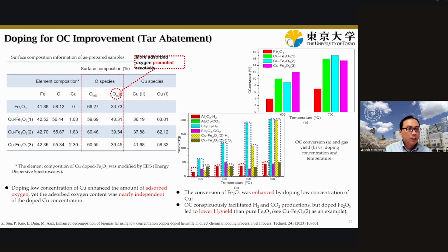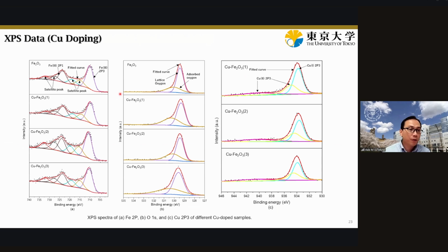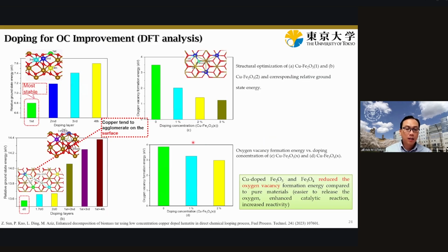This is also confirmed by XPS data: by doping copper into the hematite itself, the binding energy for the adsorbed oxygen atoms is increased compared to the lattice oxygen itself. And we can also understand that the copper-doped iron oxide can reduce the oxygen vacancy formation energy. So from these, what we expect is that it becomes easier to release the oxygen, it enhances the catalytic reactions, and finally we expect it can also increase the reactivity itself.